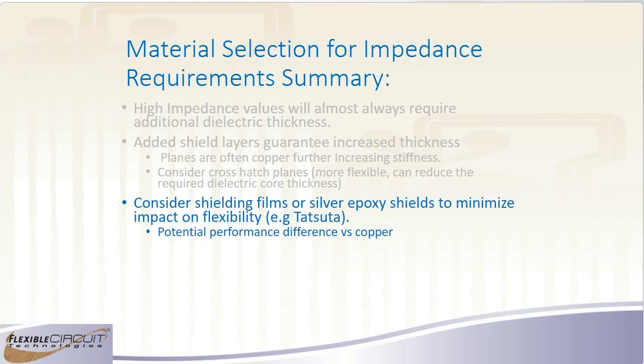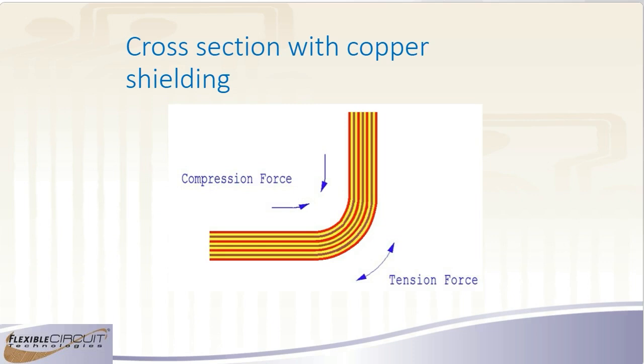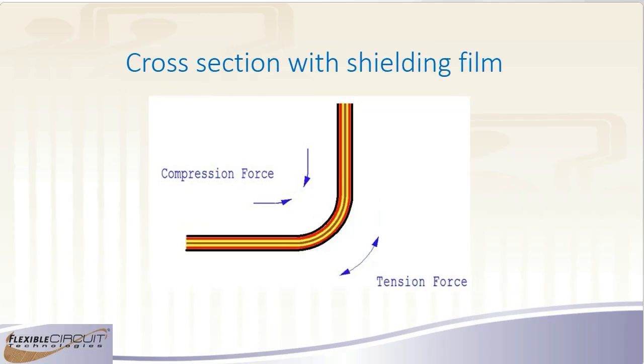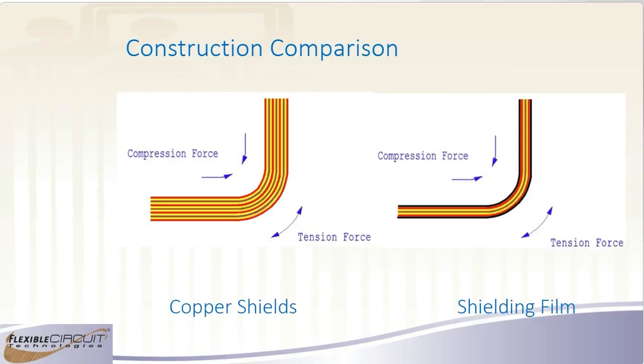So if you look at this picture right here, this is a cross-section of a multi-layer circuit that has a single layer of copper and two planes, and those are assuming that you're using copper planes. You can see the overall thickness. Now, if we were to eliminate those two outer copper planes and put in the shielding film, this is what it would look like, and this is pretty much to scale. And so you can see that you're significantly reducing the overall thickness of the circuit. So that's going to give you a lot better flexibility and still give you good isolation and impedance requirements that you can meet.